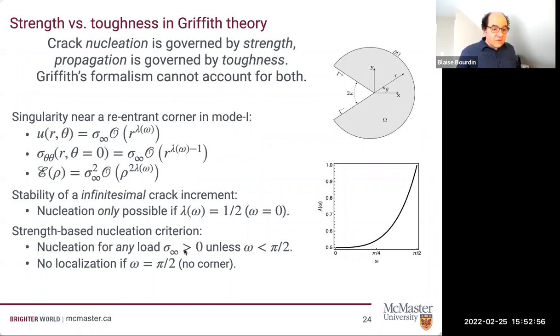And worst of all, lambda equals 1/2 corresponds to a crack. So in Griffith's theory, if you don't have an initial crack, you will never get a crack. But at the same time, if you have simply a notch like that, your stress will be infinite. So if you believed in the concept of strength, you would have to nucleate a crack for any non-zero loading. And okay, we're mathematicians, so it makes sense. Having a criterion that is based on a pointwise gradient of a function in W^{1,2} makes absolutely no sense.